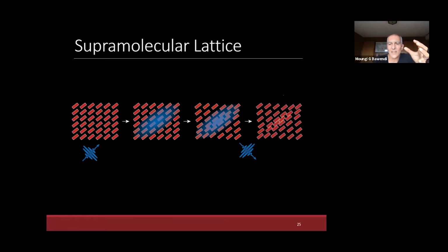And this structural transformation due to the interaction between the exciton and the lattice can stick around for quite a long time. In fact, when we turn off the light, it takes many hours for the photobrightening to disappear.